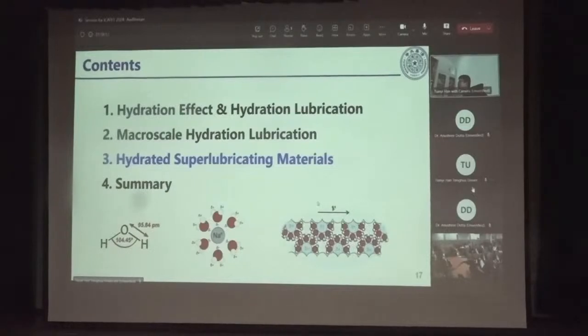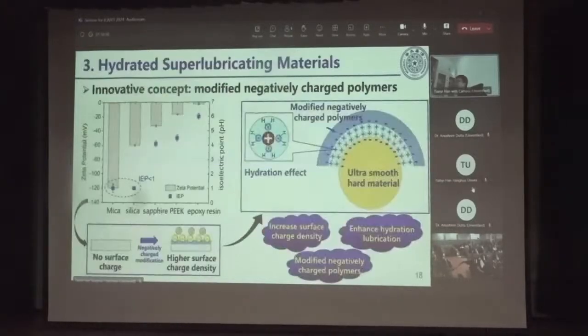Next, based on the scientific research, I will introduce the application of the hydration lubrication. In the previous test, we used sapphire, silica, or mica, and we can find that these materials are all negatively charged. But for some materials, such as PEEK or epoxy resin, their surface is less charged in water, with very low surface potential. In order to enhance the hydration effect, we need to increase the surface potential of these materials. If we can modify the material by grafting some charged groups or polymer brushes on the surface, such groups or brushes will be negatively charged in water.